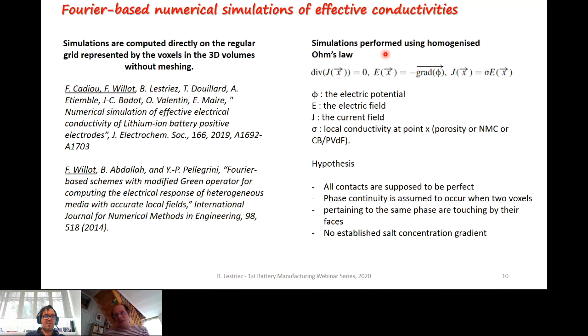So to calculate the effective conductivities, we have used the simple homogenized Ohm's law, where each voxel was given the conductivity of the phase that makes up this voxel. In terms of hypotheses for electronic conductivity, we've considered all contacts to be perfect. And we have also considered phase continuity, which is assumed to occur when two voxels pertaining to the same phase are touching by their faces. And we have also considered, obviously, no established salt concentration gradient, which is an oversimplification with respect to what's going on in an electrode under operation. However, I think that what we saw can be clearly transposed to what's going on when there is the establishment of a concentration salt gradient.